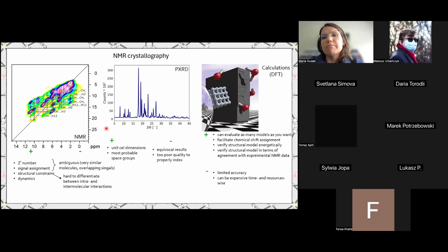We might argue that there are some different techniques. We can solve the structure from powder, that's true, but we also have problems then with hydrogen atoms. We have micro electron diffraction. This is an excellent technique, but it is capricious, so it's not always easy to get a crystal. Micro ED actually has problems opposite to single crystal X-ray diffraction. Many crystals are too large for it. We also have severe radiation damage. So this is also not a universal technique that we can use for all the solids.